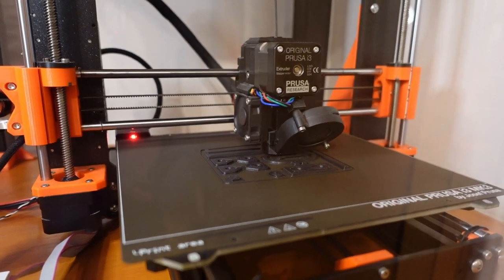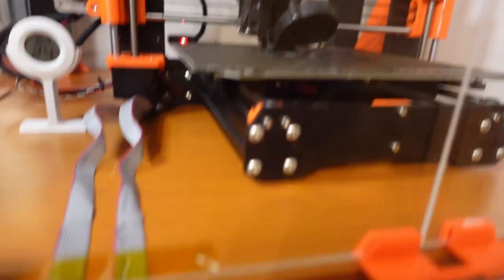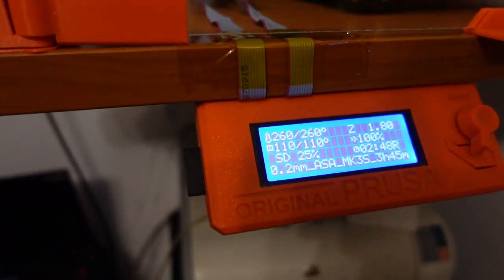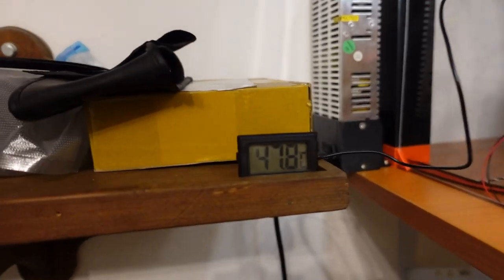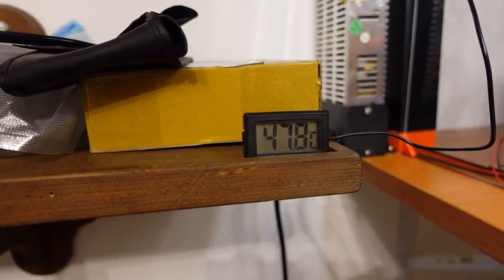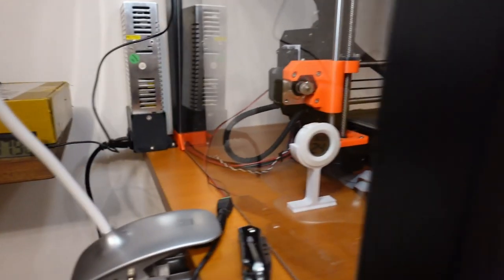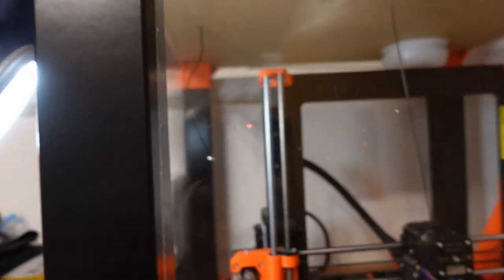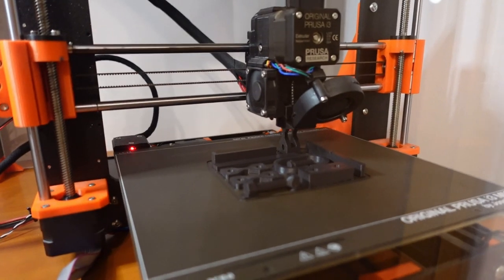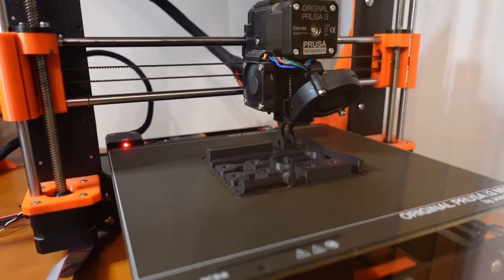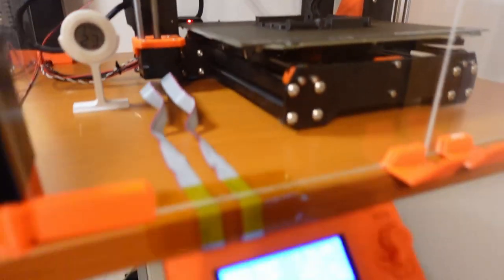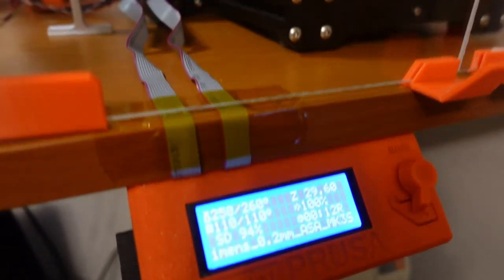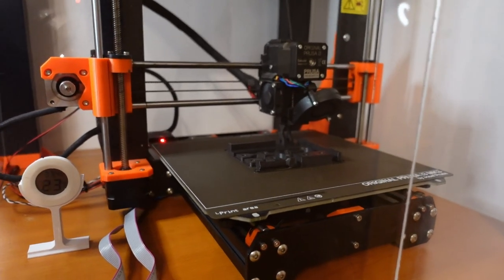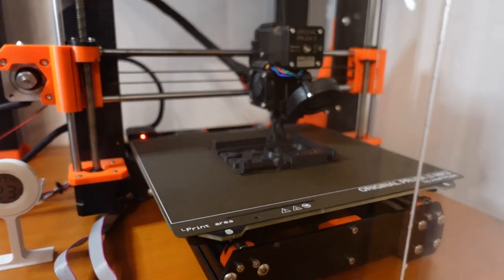So after 1.5 hours you can see the progress, and there will be maybe 3 hours more printing. And after 1.5 hours the temperature stabilized around 48 degrees Celsius inside. And there is the sensor in this position. Those two objects for the layer adhesion test are the last ones, and printing will be finished in approximately 12 minutes. And the temperature inside the enclosure was constantly 47 degrees Celsius.